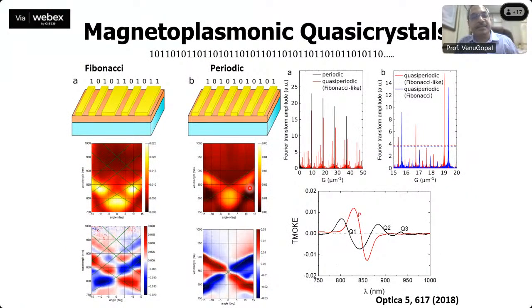So you can have a plasmonic quasi-crystal. Instead of having a periodic grating-like structure, you can have this Fibonacci type structure where the widths are modulated as per the Fibonacci sequence, and that leads to a broadband or multiple resonances at which this structure can respond, compared to a single resonance which a plasmonic crystal shows.